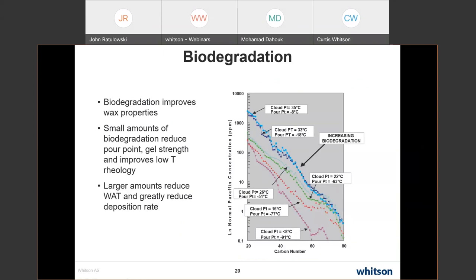So this is a nice plot. It originally came from Shell, and it shows some oils at various degrees of biodegradation. So the base oil with no biodegradation might have a normal paraffin wax profile that looks like this, and they have appreciable cloud point numbers. These aren't high pour point oils, so the pour points are still pretty low.